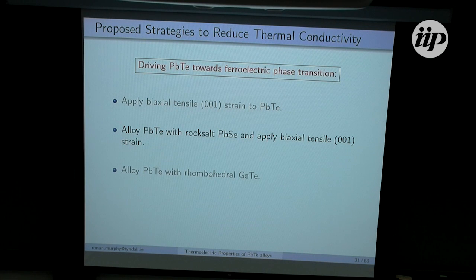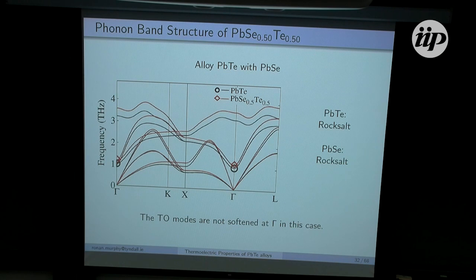So now I'll move on and talk a bit about the second approach, which is to take lead telluride and alloy it with a rocksalt material, lead selenide, and then apply biaxial tensile 001 strain to this. Just to mention, we use the virtual crystal approximation to model our alloys. And here I have the phonon band structure of lead telluride in black, and this lead telluride, lead selenide alloy in red, about a 50-50 mixture.